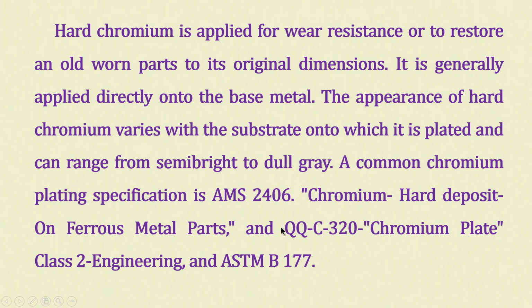If I keep on coating more and more, the shine will go off. So, it is always preferable to do the coating with the minimum quantity if you want a very good shine. If you do not want a very good shine, go for medium quality, that is extra deposition. Extra deposition also will give you strength for use subsequently. So, a common chromium plating specification is AMS 2406, chromium hard deposit on ferrous metal parts, that is the title, and QQC 320 is another standard, that is chromium plate class 2 engineering, and ASTM B 177 is another.